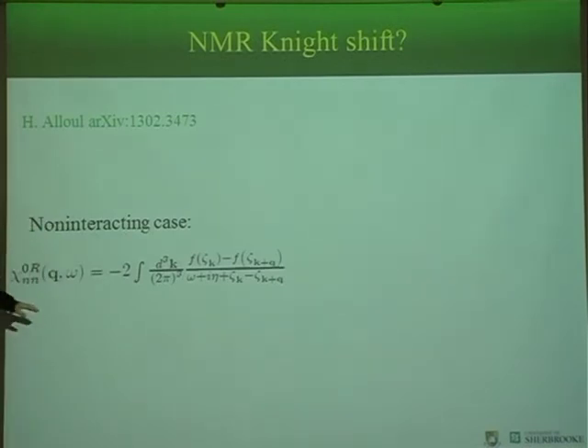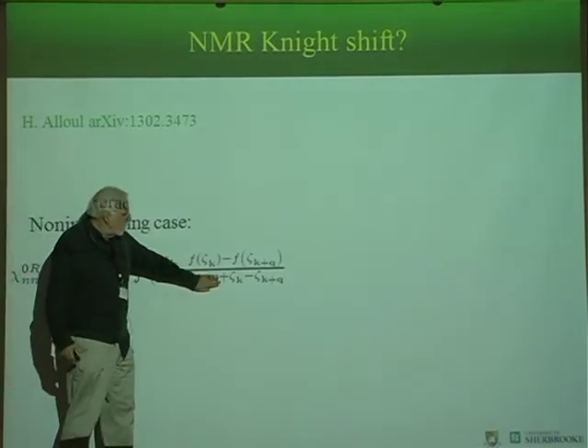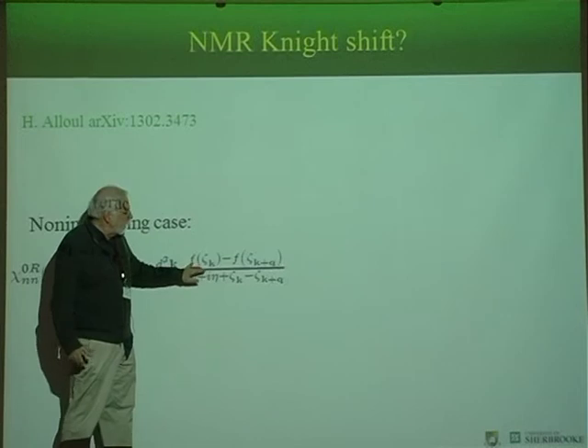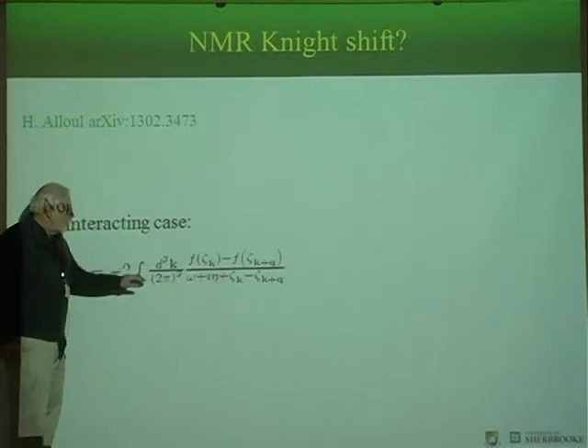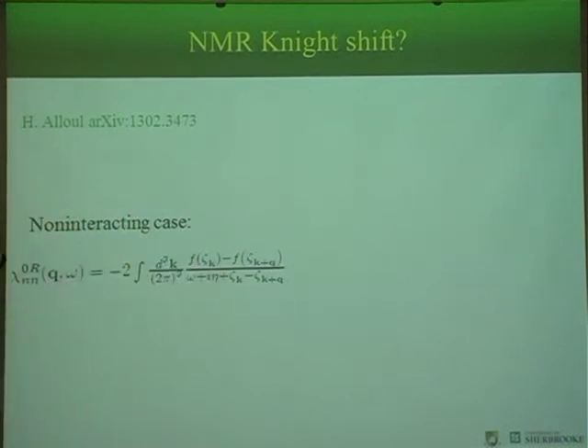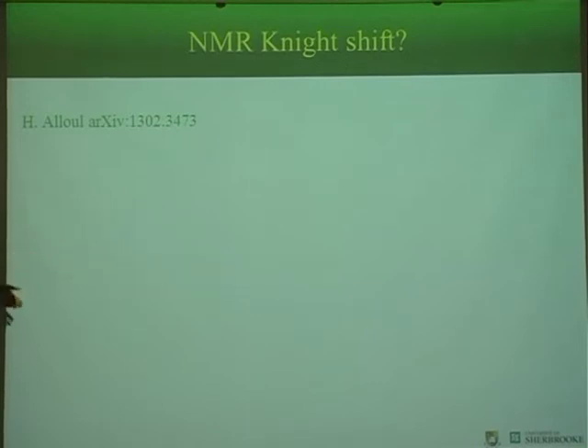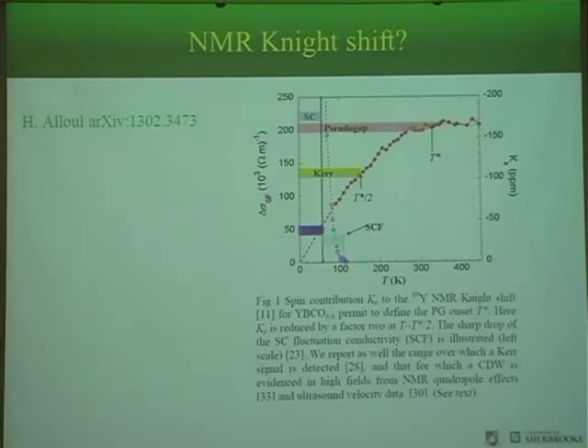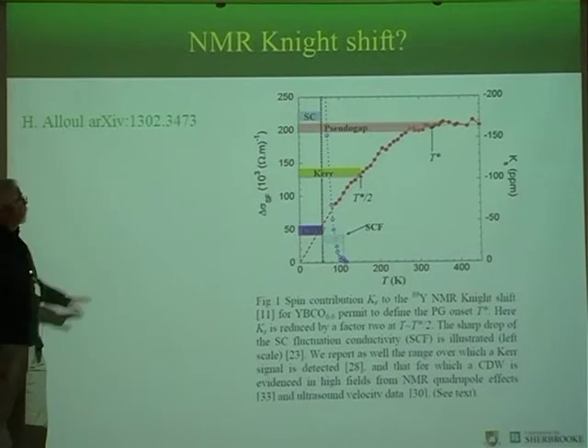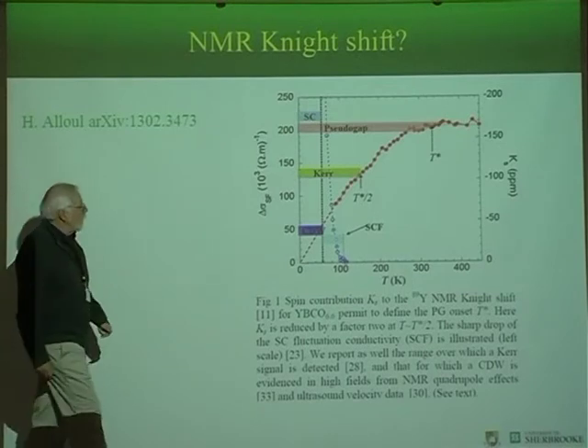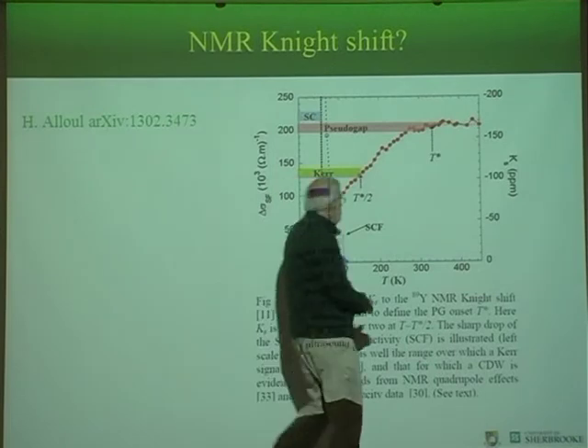And in this case, you see that when omega equals 0 and q goes to 0, this is a derivative of the Fermi function. The integral just gives the density of states. So in the non-interacting case, or the Fermi liquid, you expect a constant on the scale of the temperature, that's on the scale of the Fermi energy. Now, the experiment is quite different. The experiment was first done by Alloul. And the point is that